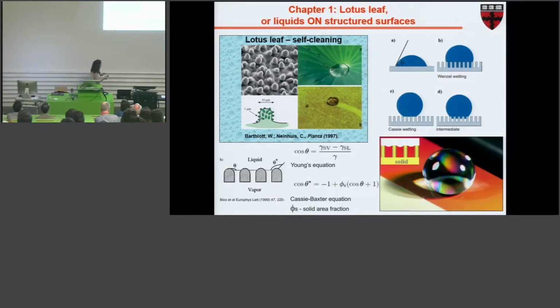Something interesting happens the moment you begin to add structure in addition to chemistry. The same surface with exactly the same chemistry, if it is structured on the nano and micro scale, will add something to the properties of the liquids interacting with it. In a very simple way, one can think of the liquid now sitting not on a solid, because its interaction with the solid is exactly the same as with the flat surface, but in a cushion of air. So it is sitting on an interface composed of both solid and air.